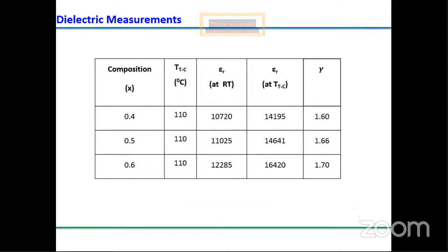Okay. Then next what we did, this is what I explained: gamma is more, and we observed the Tc, and the dielectric constant value is higher at 0.6. So naturally, the polarization value should be high. So after that, we measured the polarization electric field hysteresis for different compositions, and also at different temperatures. This diagram shows PS versus temperature. Here also you see PS slightly increases up to 40 degrees, then sharply decreases, linearly decreased, and then it becomes saturated.